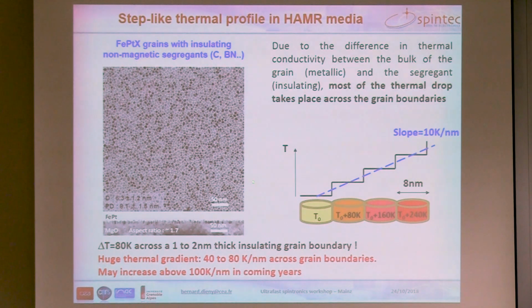Now, if we look again at the structure of the media, it is composed of metallic grains surrounded by insulating grain boundaries. Because the thermal conductivity in the bulk of the grain is much higher than the thermal conductivity of the grain boundaries, the temperature along this bunch of grains is a kind of step-like function. Most of the drop of temperature occurs across the grain boundary, not across the bulk of the grains.